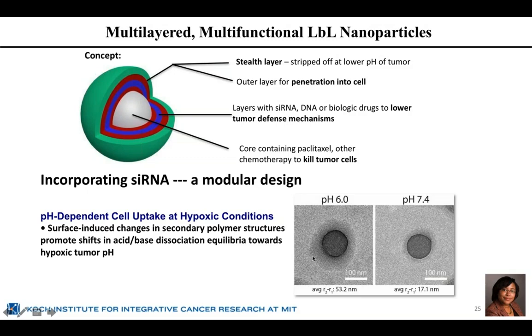So at a pH of 6, for example, we have a relatively neutral nanoparticle that is soft and squishy because of the swelling of the layers. And it turns out that cells will much more likely take up these neutral nanoparticles than the strongly negatively charged water-shrouded ones. So we can take advantage of this because tumors tend to be hypoxic. They're not great at getting oxygen to their core, and so their pH is somewhat lower. And in those hypoxic conditions, the nanoparticle transforms into a sticky nanoparticle, and we therefore can get enhanced uptake.